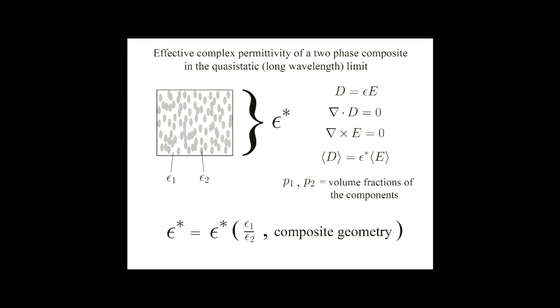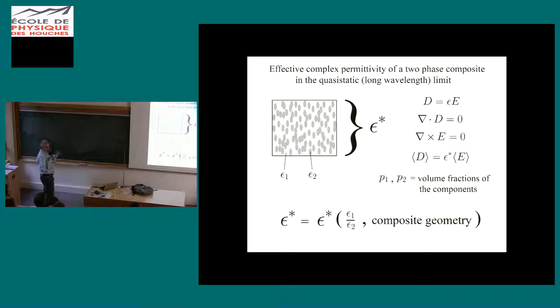And so the quasi-static formulation of Maxwell's equation, so this is long wavelength, where the wavelength is very long compared to the microscale, to the scale of the inclusions. So here's the basic constitutive law that the displacement field is the complex permittivity times the electric field, divergence-free, curl-free, and so on. And this defines the effective complex permittivity, the macroscopic version of that local law. And then the effective complex permittivity is a complicated function of the ratio of the component permittivities of the brine and the ice, as well as the composite geometry.